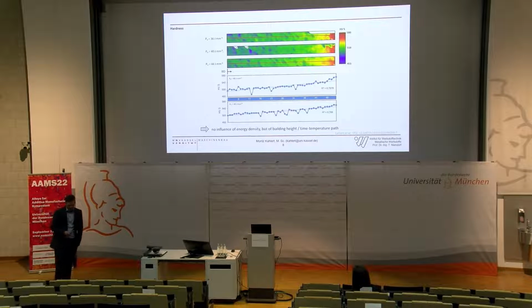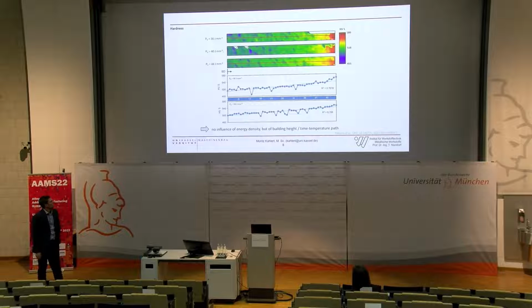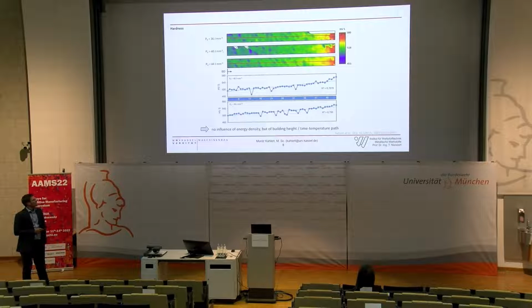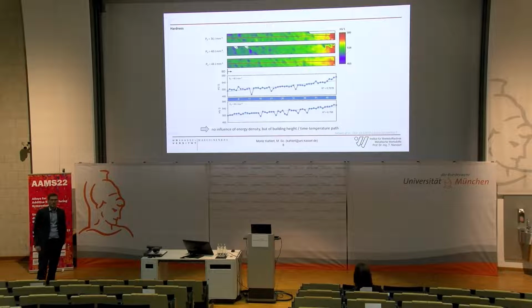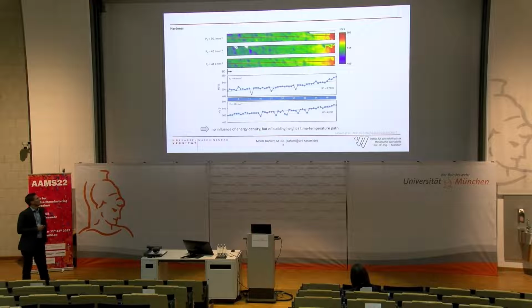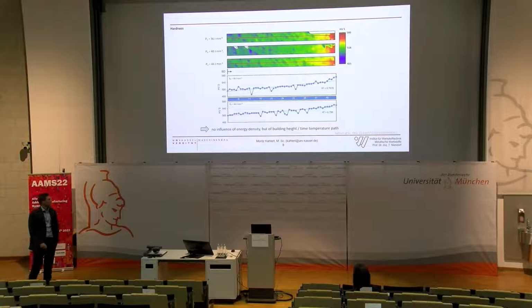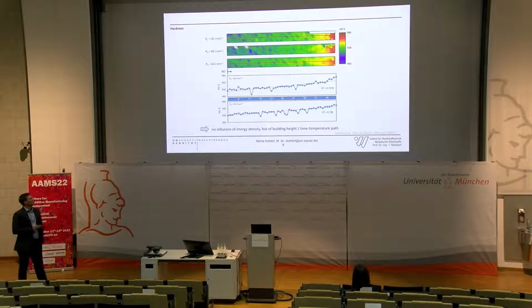When we look at the hardness, we can see that there is no influence of the process parameters, but there is an influence of the build height. In the uppermost layers, there is a higher hardness than in the lower layers, and this comes from some annealing processes in the lower layers and some quenching in the upper layers, resulting in this hardness. The line measurements also show these results.